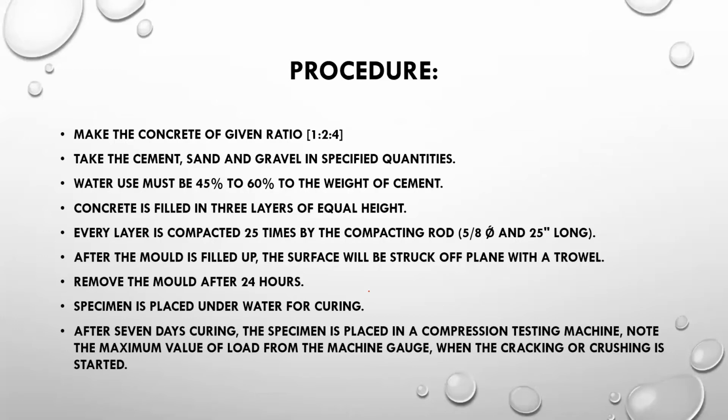Surfacing should be good. A specimen is placed under water for curing. Remove the mold after 24 hours. So what we have to do: a specimen is placed under water for curing. After 7 days of curing, the specimen is placed in a compression testing machine. Note the maximum value of load from the machine gauge when the cracking or crushing starts.